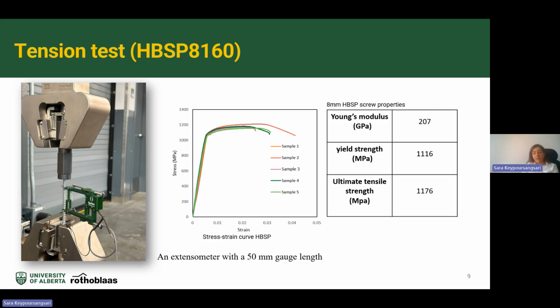We made special grips and fixtures to make sure that our experiment is based on the standards. And also we used a 50 millimeter gauge length for the extensometer. We found the load displacement, and based on that, we found the stress-strain curve for these self-tapping screws because we need some inputs such as Young's modulus, yield strength, and ultimate tensile strength for our simulation.